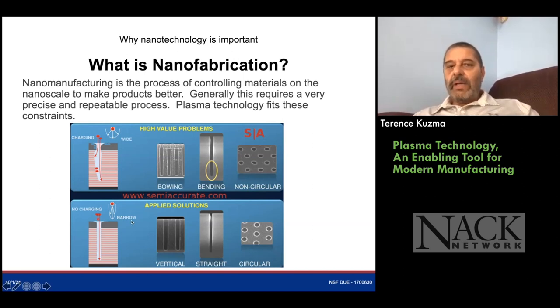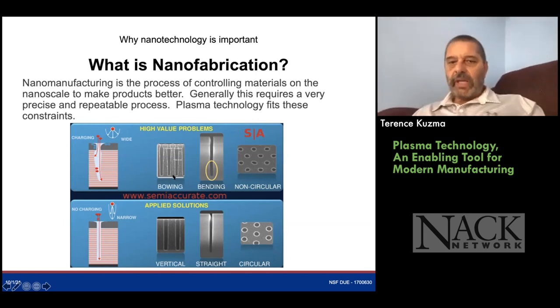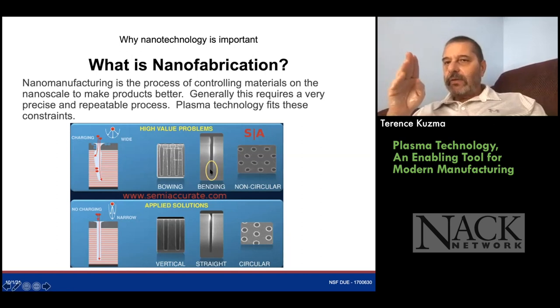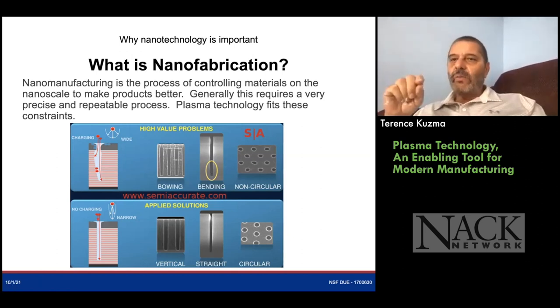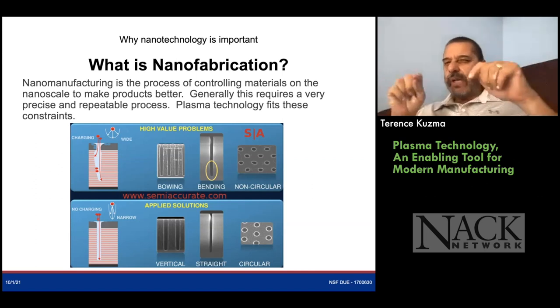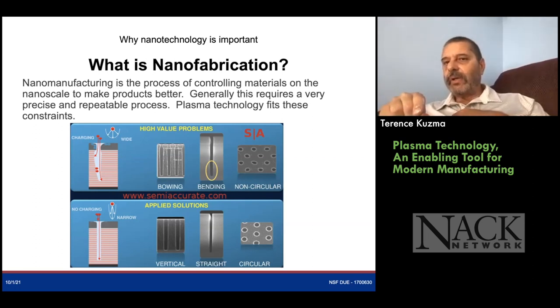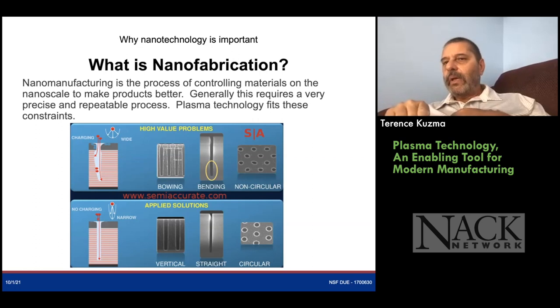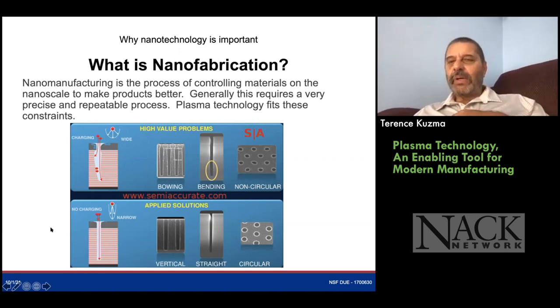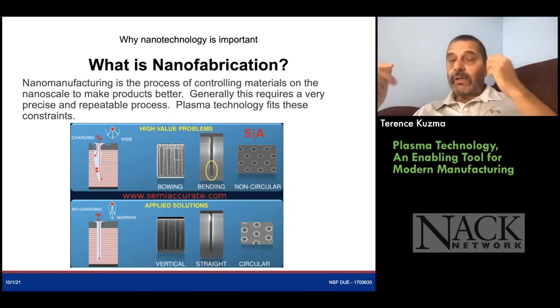When you're trying to make the rectangle and it starts looking like a carrot — that's bowing, and that's not good. You can also have bending in the etch, which sometimes comes from charging inside the wafer. And when making things on a three-dimensional scale, if you're trying to make something perfectly circular but you're making elliptical things, that would also be bad. These defects all occur on the scale of a transistor.